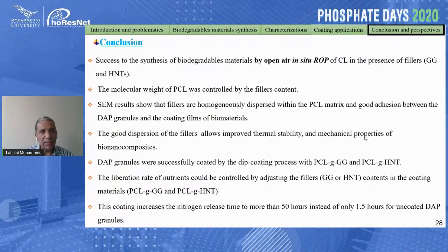As a conclusion, during this study, we succeeded in preparing the cyclic ester polymer in the presence of the filler in open air. We get really high molecular weight. The results show that we have a good dispersion of fillers inside the polymer, allowing good thermal stability and mechanical properties, and the granules were successfully coated by dip coating with PCL guar gum or PCL grafted halloysite nanotubes. The release rate of nutrient could be controlled by adjusting the filler contents, guar gum and halloysite nanotubes, and this coating increased the nitrogen release time to more than 50 hours instead of only 1.5 hours for uncoated granules.